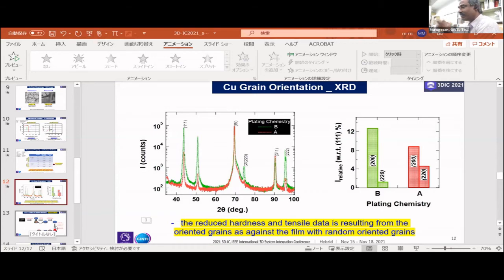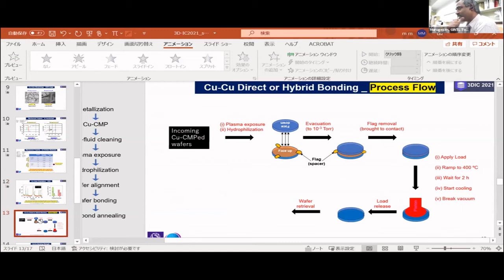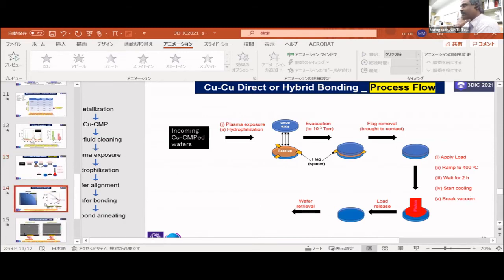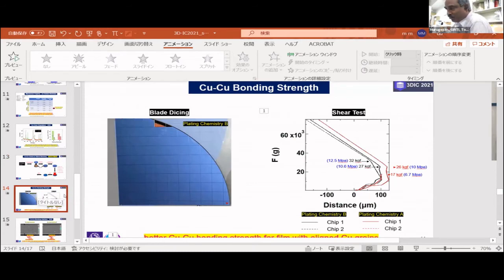So how will this work for our copper-copper direct or hybrid bonding? Basically we did our copper-copper direct bonding after applying load at 400 degrees Celsius and annealing for 2 hours. And this is the typical one. We checked the copper-copper bonding strength in two ways: one using blade dicing, another the shear test. After copper-copper direct bonding, we diced the wafer into 10 millimeter by 10 millimeter dice.